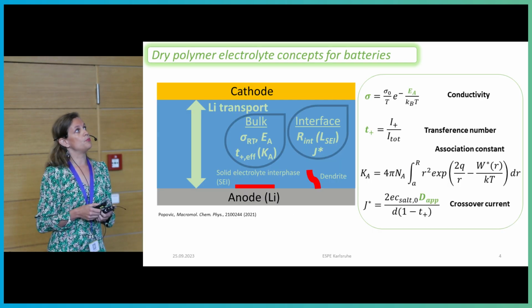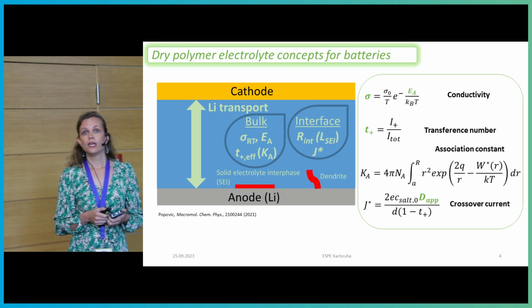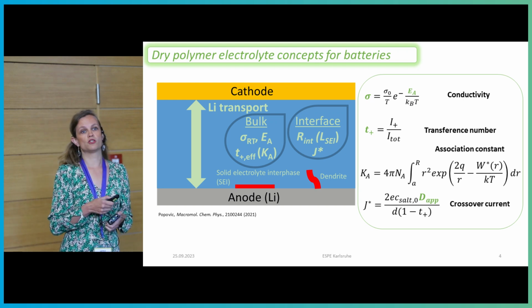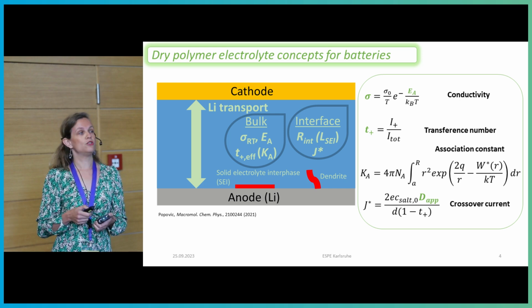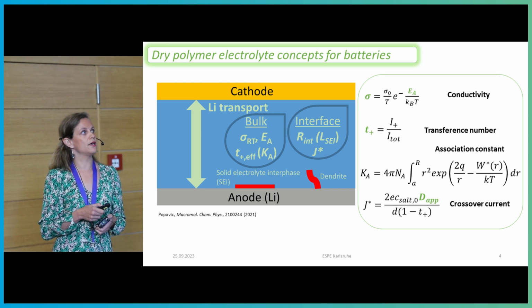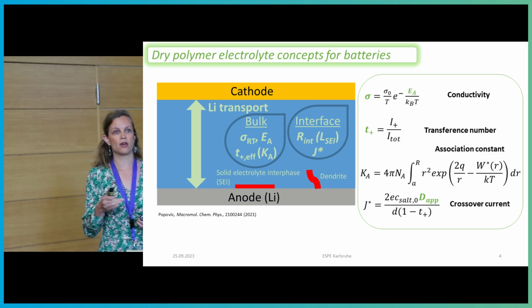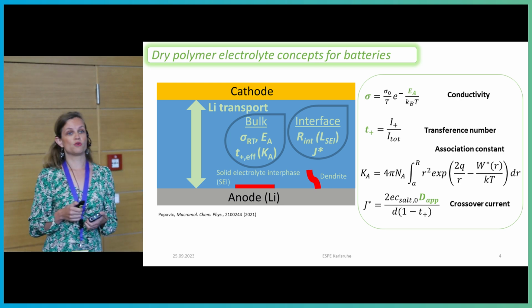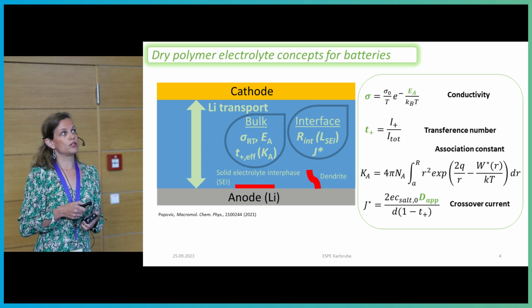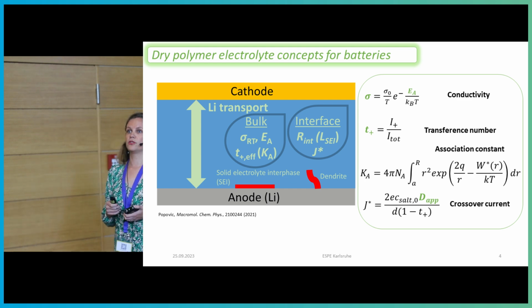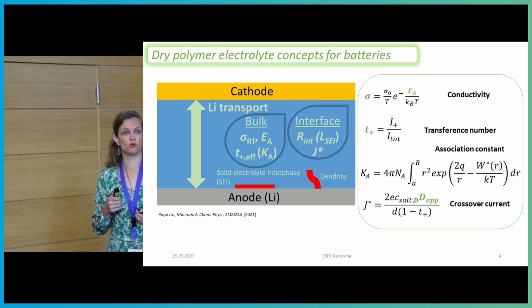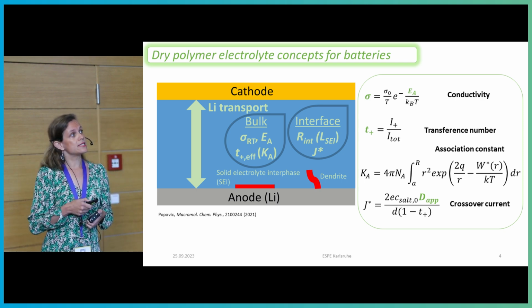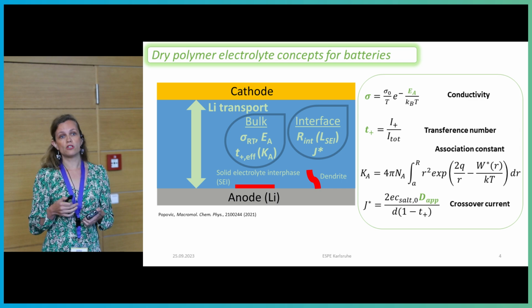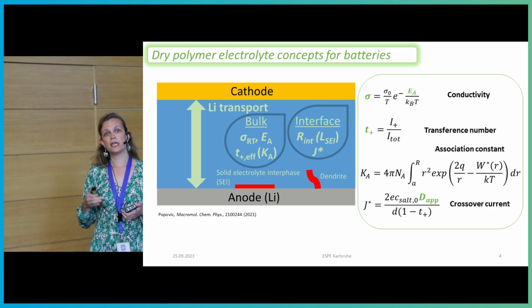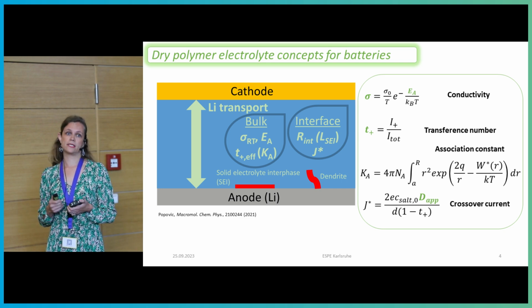So if we think about dry polymer electrolytes, conceptually, we are trying to improve both bulk and interfacial properties. And that means we need to have very high ionic conductivity that is at the end related with activation energy. So we need to have those as low as possible in order to have a good ionic transport. We heard a lot about transference number. We're trying to have materials that transport only cations, obviously, and the anions should be immobile. And in that sense, it's important to understand that the association constant that we have in both our liquid and polymer electrolytes is a very complex thing.